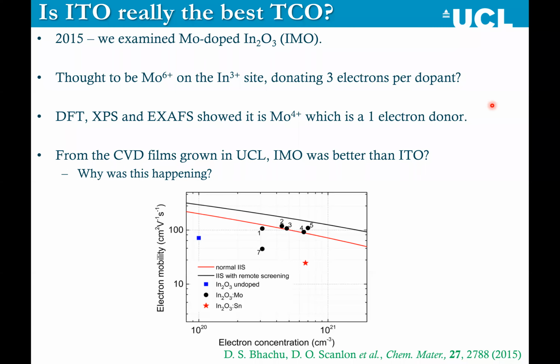But from our analysis of the mobilities of the chemical vapor deposition grown films from UCL, what we found was that IMO was actually continuously being found to be better than ITO. And in fact, these results were actually breaking what we call the ionized impurity scattering limit. So they were breaking the rules that we had for conventional doping in transparent conducting materials. And we couldn't really understand why.